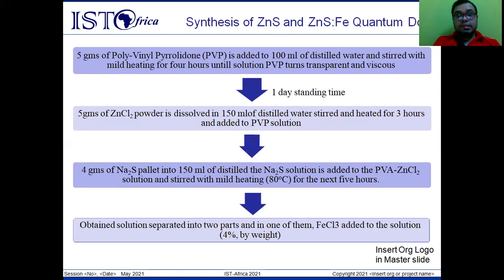First, the chemical synthesis process of zinc sulfide quantum dots. We use a simple one-pot chemical synthesis method. The capping matrix used here is PVP, that is polyvinylpyrrolidone. The main function of this PVP is to control the size of the quantum dot, because the growth of the quantum dot takes place in the interstitial gaps of the PVP, while PVP does not itself take part in the reaction.